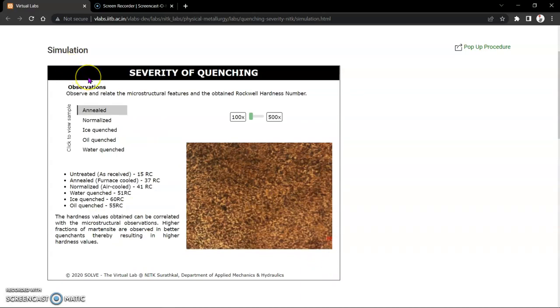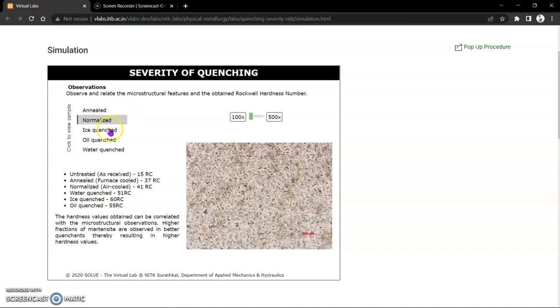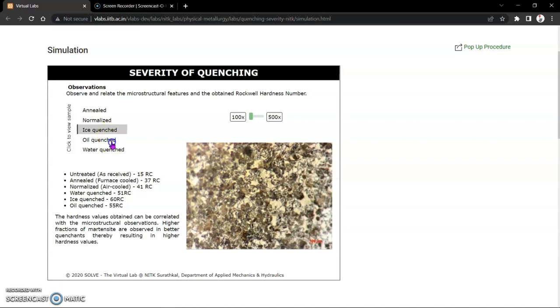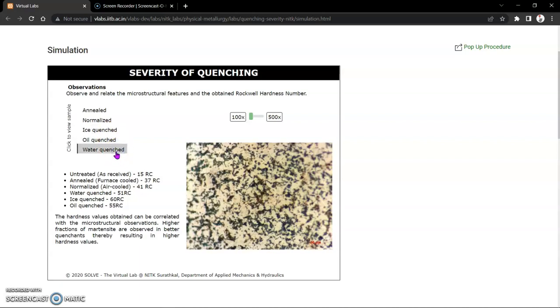The observation of the experiment is to observe and relate the microstructural features and the obtained Rockwell hardness numbers. This is for the annealed, normalized, ice quenched, oil quenched, and water quenched. The hardness values obtained can be correlated with the microstructural observation. A higher fraction of martensite is observed in better quenching conditions, thereby resulting in higher hardness values. Thank you.